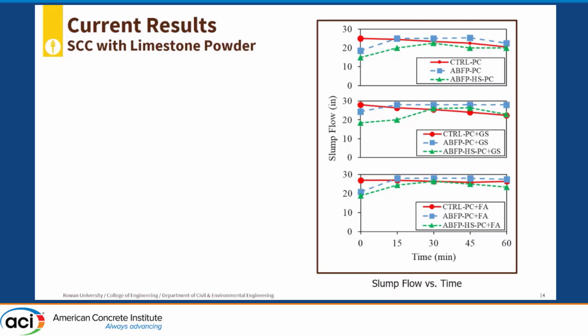So this graph is the slump flow versus time graph. At the top is the SCC with Portland cement only. In the middle is the one with the slag replacement. And then at the bottom is the one with fly ash replacement. The red ones correspond to control mixtures, mixed, cast, and cured at 20 degrees Celsius. The blue and the green ones are mixed, cast, and cured at -5 degrees Celsius. Both of them have ABFP, but the green one has an added hydration stabilizer.